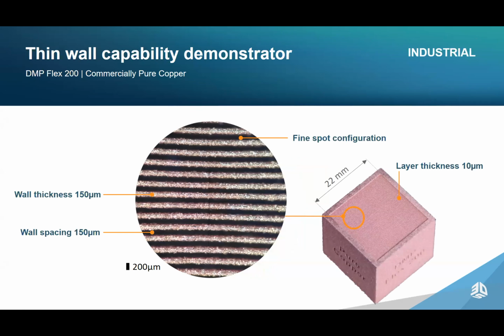And one other thing is we do offer a smaller volume system. I'd say that our Flex 350 and our Factory 350 are our bread and butter mid-frame systems. We also offer the DMP Flex 200, which is a slightly smaller system with a really fine spot size. So we're able to not only cover the high-speed production copper applications where general layer thicknesses satisfy the need, but we also worked very hard to do super thin wall thickness, 150 micron and lower. But that's only available on our Flex 200 because of the special optical configuration. It's got a smaller spot size. We use a compressive roller, and we can do thinner layers with thinner, smaller powder. So we're really able to cover the different applications and needs, fine features, high precision, and in one range, a massive amount of different materials available in our mid-frame workhorse.